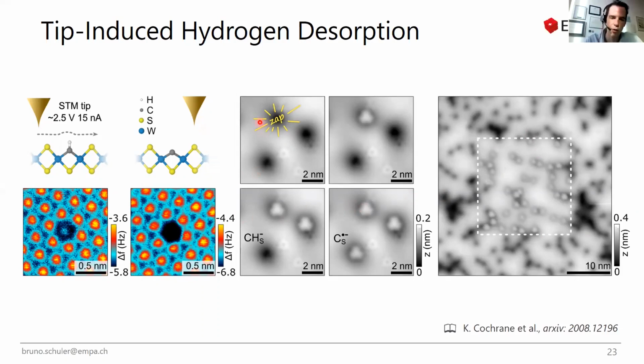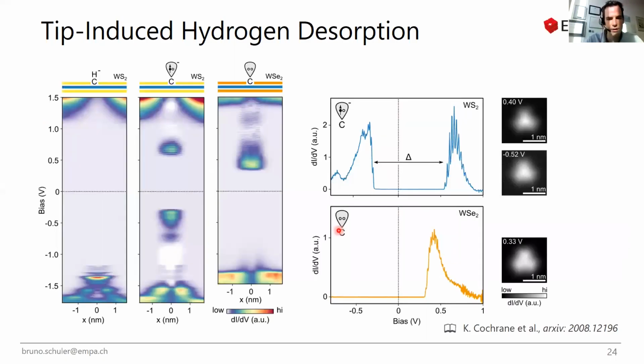And how do we know that we actually remove the hydrogen? Why is it not simply a vacancy and so on? This is the electronic signature, or the electronic footprint, that really tells us what is happening. If we go first from this carbon hydrogen complex, which is negatively charged, we see all these hydrogenic states, but other than that, no states in the band gap, which is expected for this type of impurity. And then during the voltage pulse, we see that two new resonances emerge, one in the unoccupied states and one in the occupied ones.